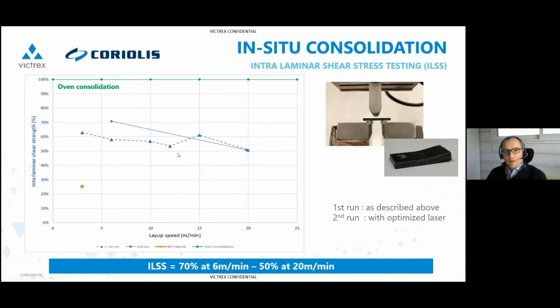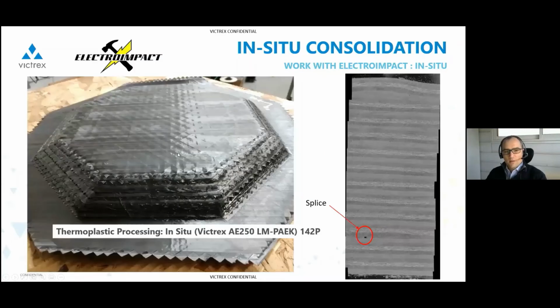As I said, we also worked with Electroimpact, which is an AFP machine manufacturer, and we did in-situ too, and we worked on this coupon here, which has 142 plies. As you can see, we can stack up all the plies together, and it was processed in-situ. Here you have the C-scan, and on the right-hand side the microcut of this part, and there's very low porosity, no voids, and just one here, but it's due to a splice. So the quality is pretty good. We've been able to stack up many plies without really damaging the quality of the panel. Pretty good results achieved here too.